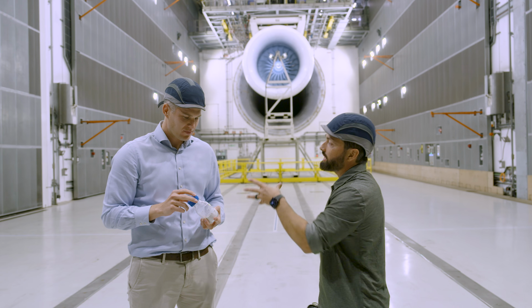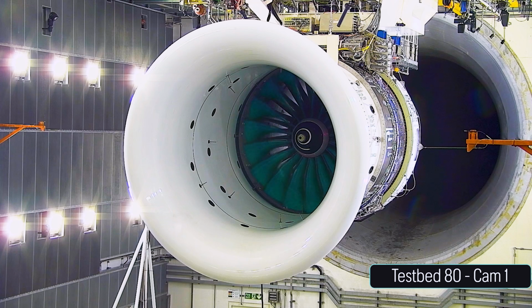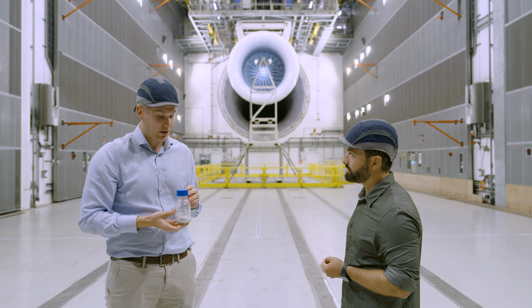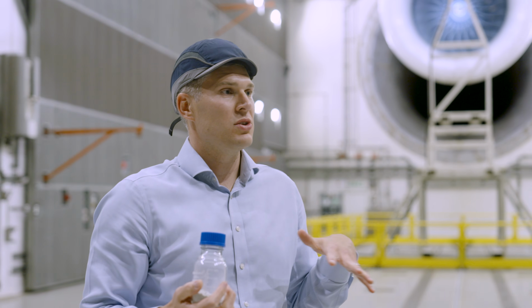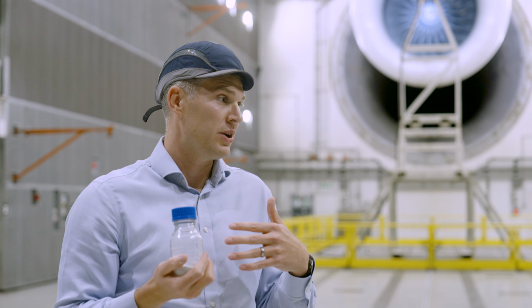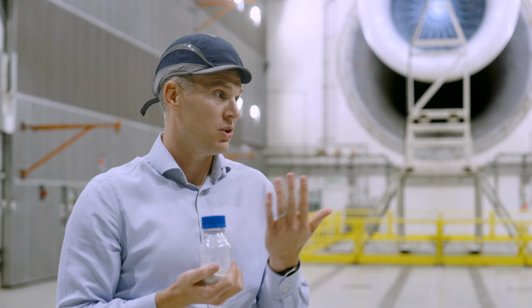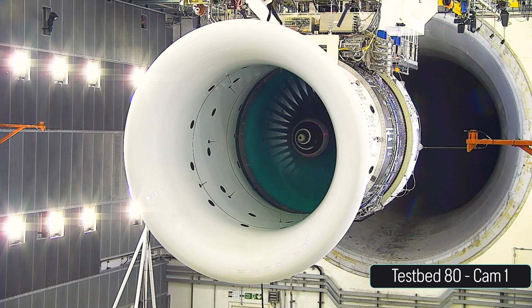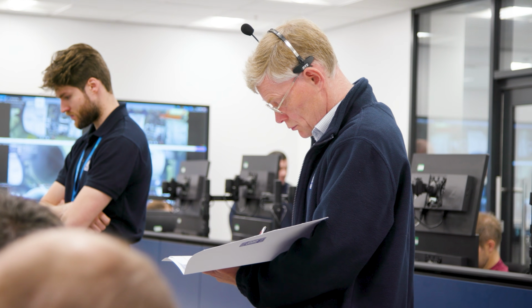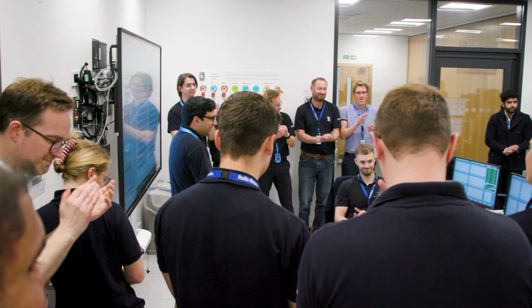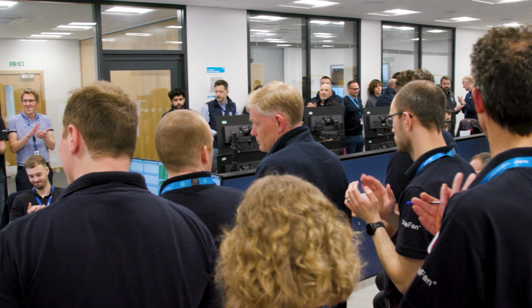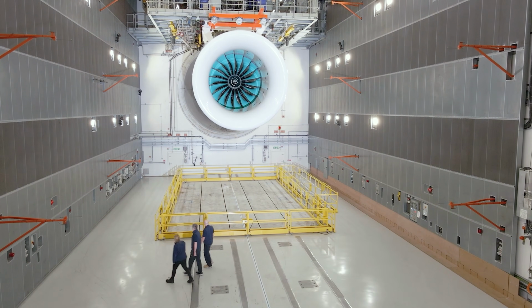So what does the dust actually do inside a jet engine? So once it gets through to the hot section of the engine and hits turbine blades, it's going to be melted. And so it sticks to the outside of our turbine components and it slowly rips layers of that thermal barrier coating off. And then you lose your temperature reduction that comes from the barrier coating, so that your nickel alloy underneath it gets hotter and hotter, and that's when it starts to deteriorate the turbine. That's why engineers at Rolls-Royce are still refining these blades, developing new ceramic coatings designed to resist molten dust and extend the life of the turbine by up to 30%.